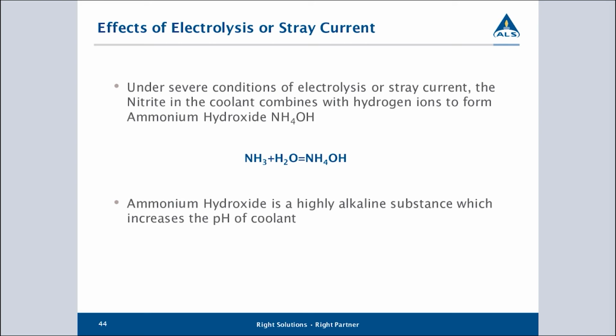One of the side effects of having stray current in the coolant is that it will degrade the glycol, and this is where your ammonia becomes pretty noticeable. So again, if you get a strong ammonia smell coming from the coolant, particularly if you open up the system to check levels and top it up, and you notice an ammonia smell, this is one of the common causes. It's either the coolant is being heat stressed, or you have stray current being driven through the coolant that's causing this process. And from the testing, we will tend to notice a rapid drop in the glycol content in the coolant.